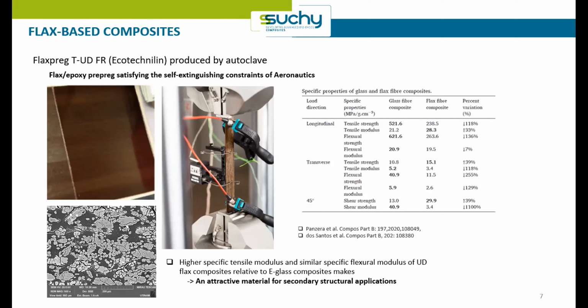A very large characterization effort was done at the University of Bristol, and you can see that the specific tensile modulus and specific flexural modulus of this material are comparable to and sometimes higher than those of E-glass composites. So it makes this material a very attractive solution for secondary structural applications.